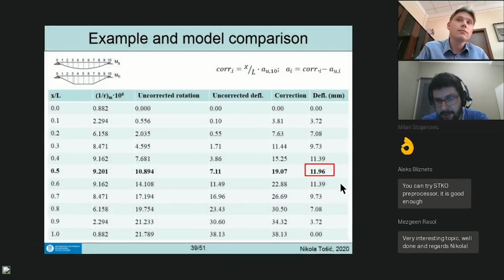And then when I apply the correction minus the uncorrected deflection, I get this. Now it's symmetrical, and I have the maximum deflection in the middle, 11.96 millimeters, for integrating in 10 cross sections along the length, which is pretty good.